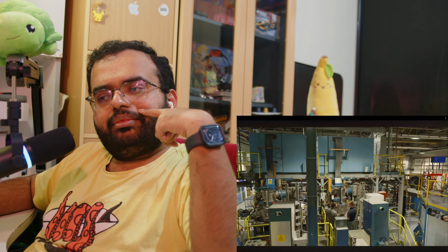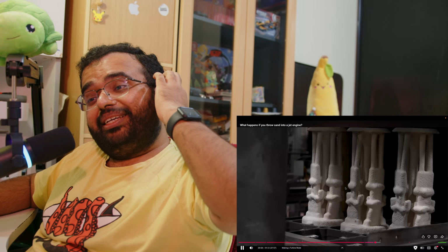And that's a really hard problem to solve because normally as a molten alloy cools, tiny crystals start to form all throughout the liquid. So you have to find some way to control them. This is one of our furnaces. They're all induction heated, there's no kind of gas fire or anything like that, and they're all under vacuum, so we only cast under vacuum in the absence of any atmosphere, but particularly oxygen. Casting is already complicated as we're casting all those elements in that specific mixture under a vacuum. Wow. Obviously, metallurgically going to cause us all kinds of problems with oxides.